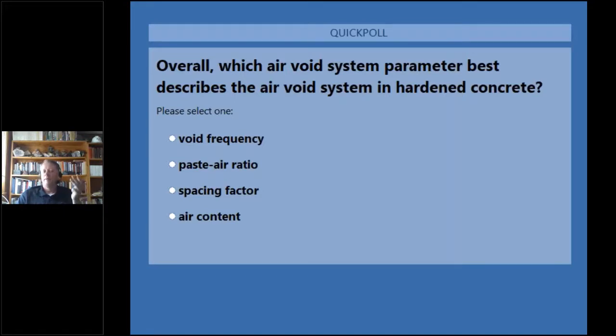There are more. Pigments, specifically dark colored or black colored pigments, the use of those in fresh concrete will make more air. Mixing time, speed, or capacity of the mixer, agitation, vibration, temperature. If the aggregate particles have dust on them before they go into the mix.